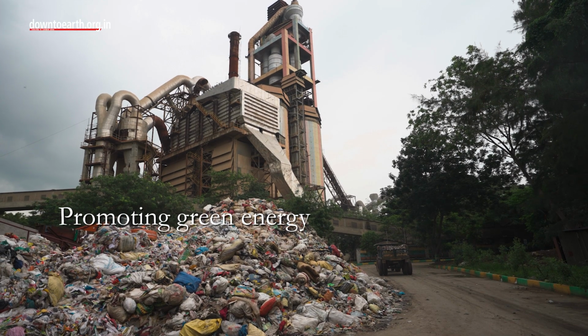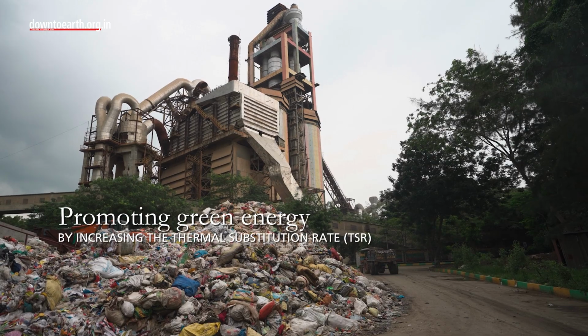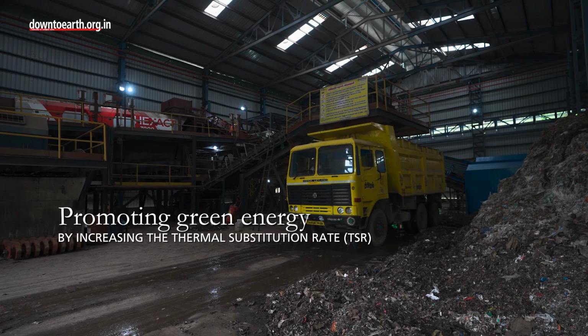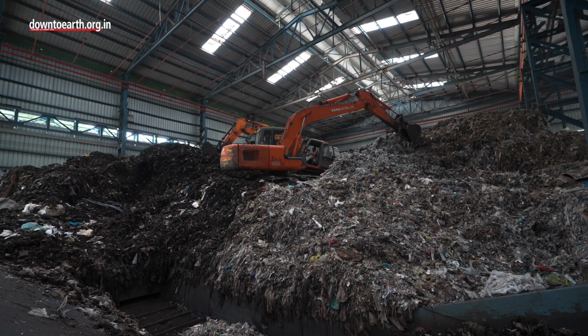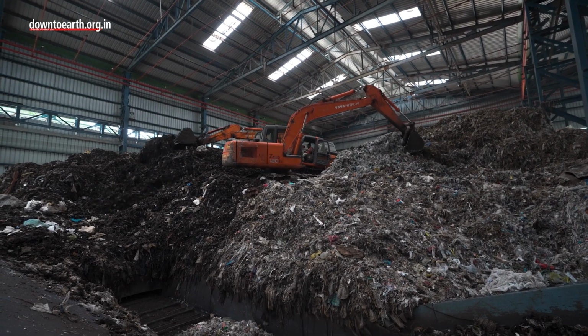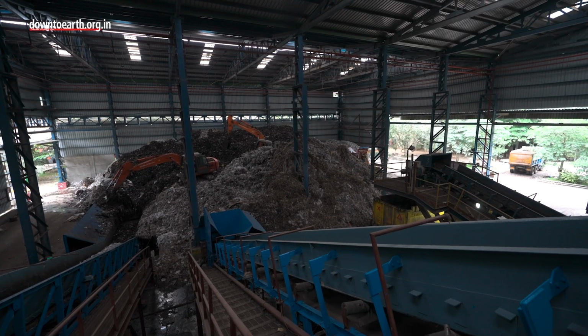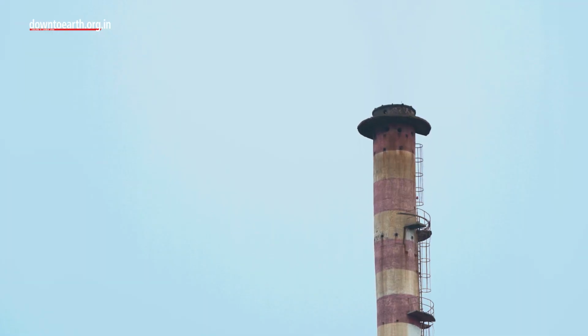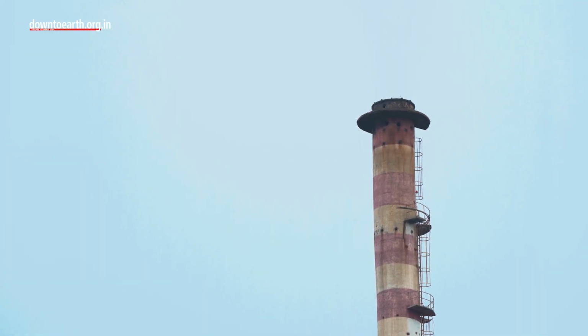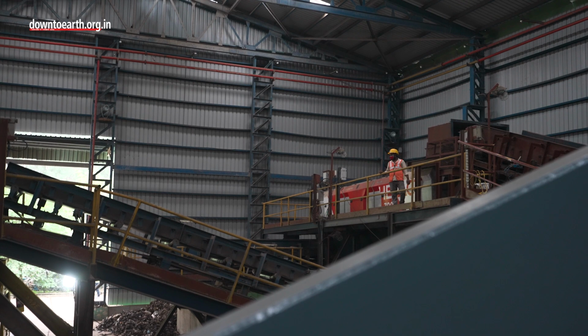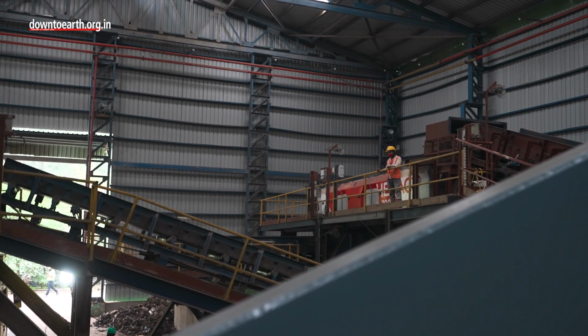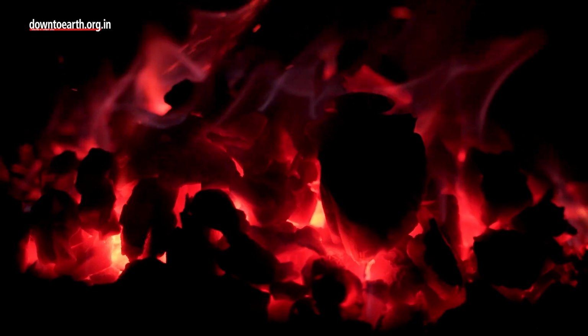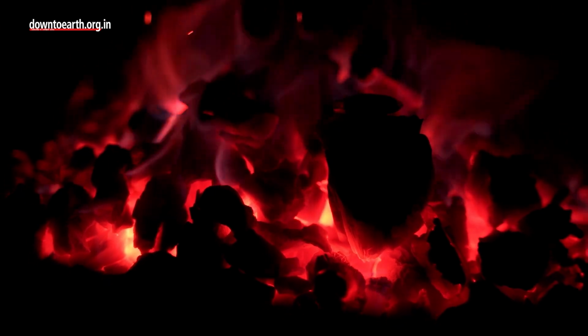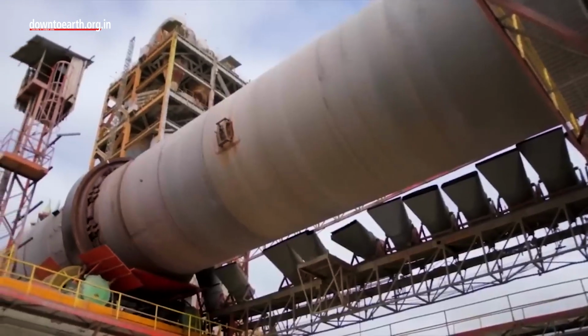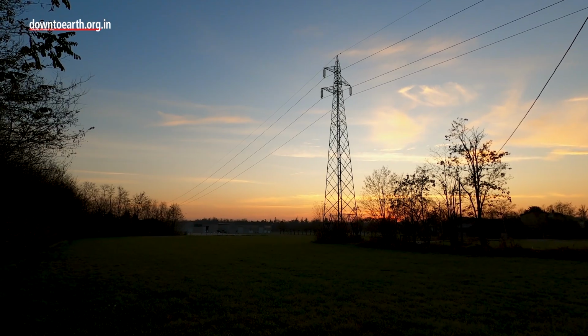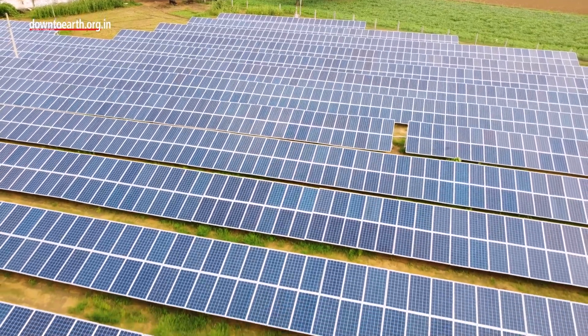Second would be promoting green energy by increasing the thermal substitution rate or TSR by replacing coal in the kiln with refuse derived fuel or RDF and other industrial waste materials. Plants like ACC Wadi and Dalmia Ariyalur have achieved TSR as high as 15 to 30%. Other steps promoting green energy would be increasing waste heat recovery, adopting kiln electrification, and fulfilling electricity requirements through renewable sources.